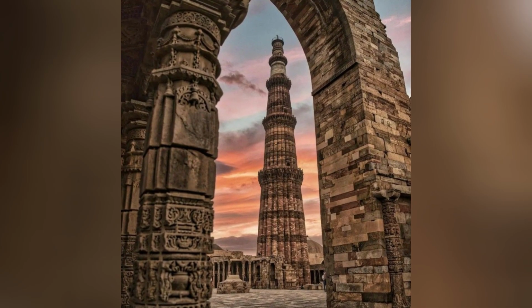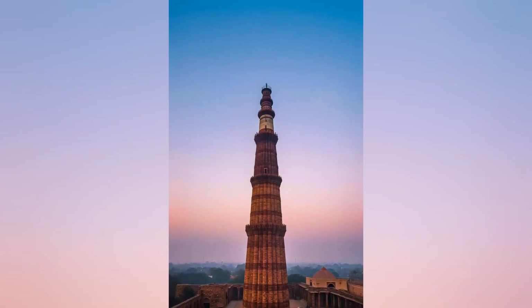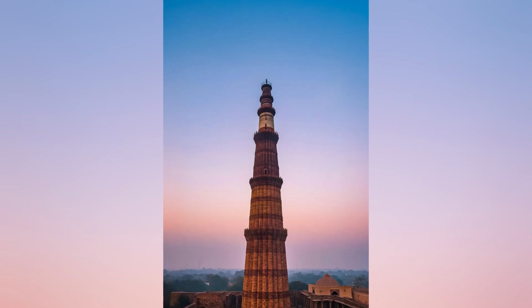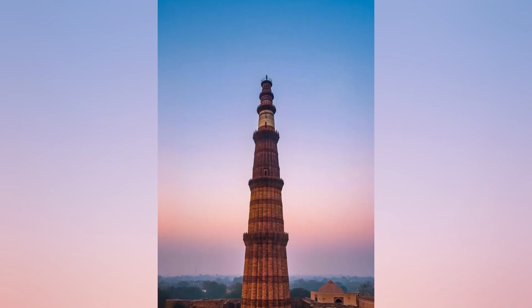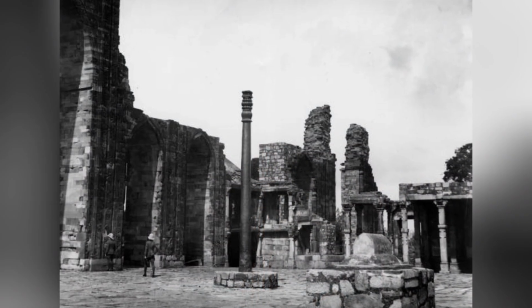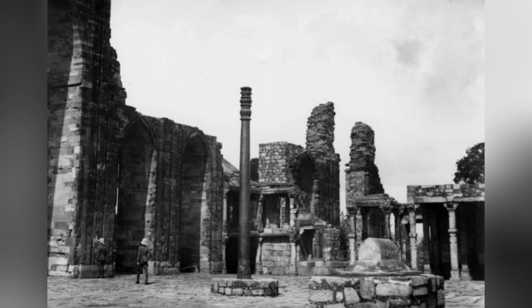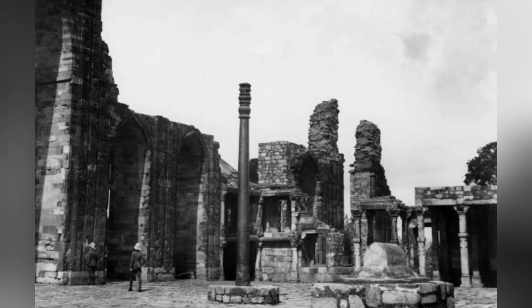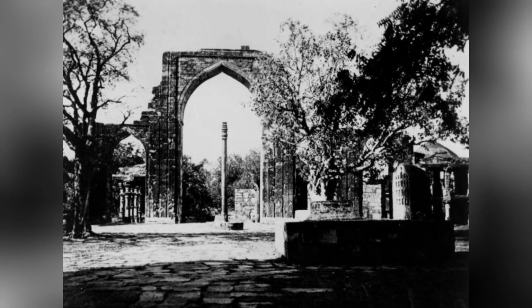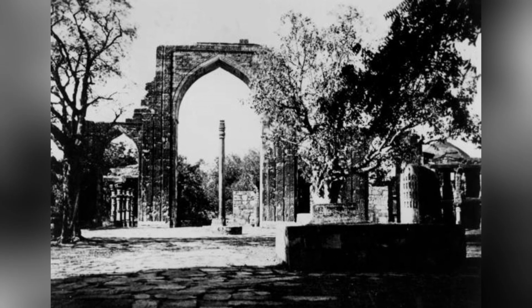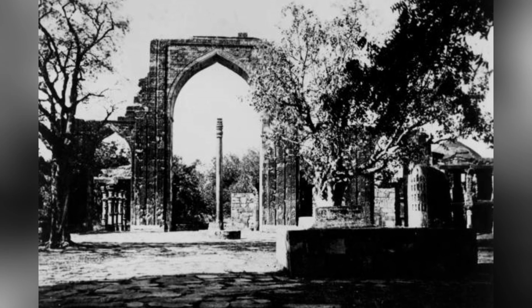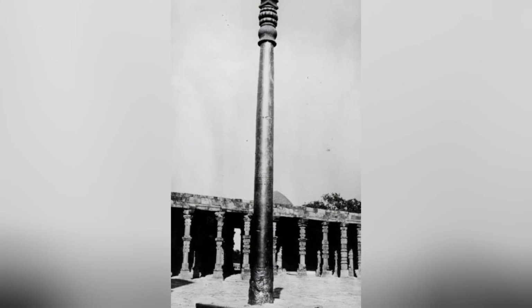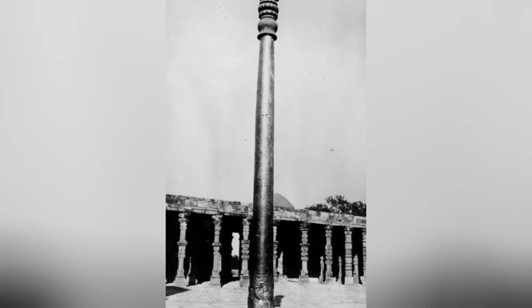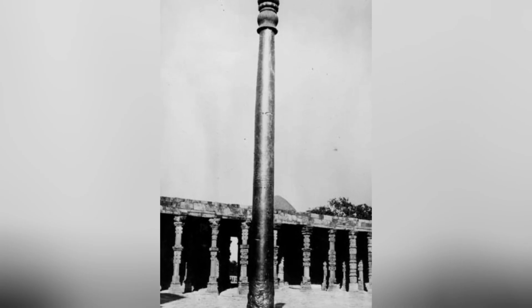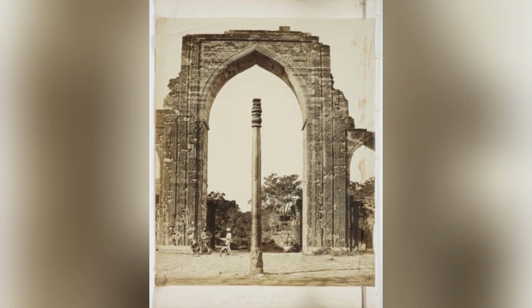The investigation of the specific conditions under which the misawite film achieves its maximum protective capability has been one of the most practically relevant aspects of the Delhi pillar research. The research has shown that the film's protective capability depends on several factors, including the phosphorus content of the iron, the frequency and the duration of the wet-dry cycles, the temperature during both the wet and the dry phases, and the presence of pollutant species in the atmosphere. The optimization of these factors, which can be controlled in a laboratory setting, but which are determined by the natural climate in the case of the Delhi pillar, is essential for maximizing the corrosion protection that the film provides.